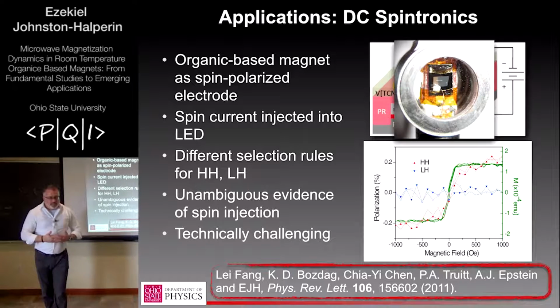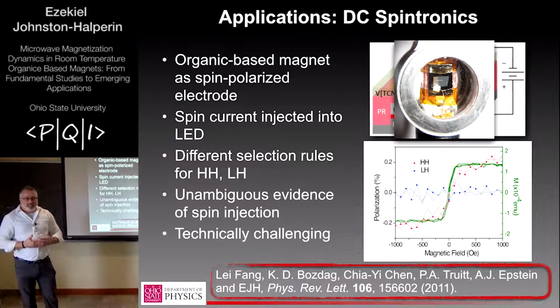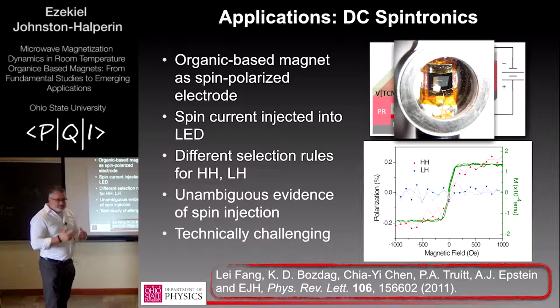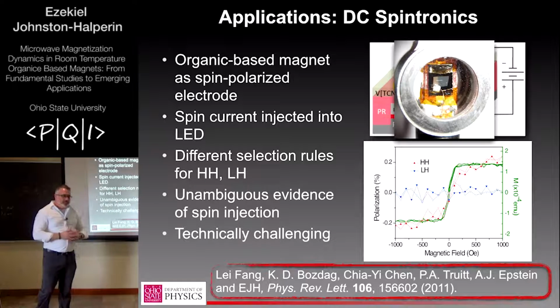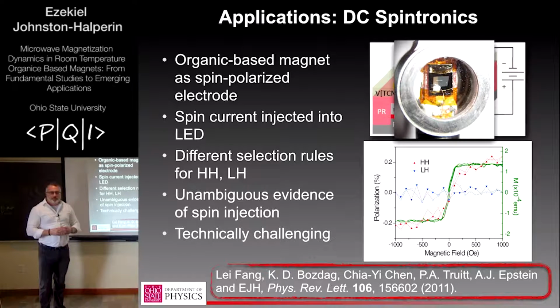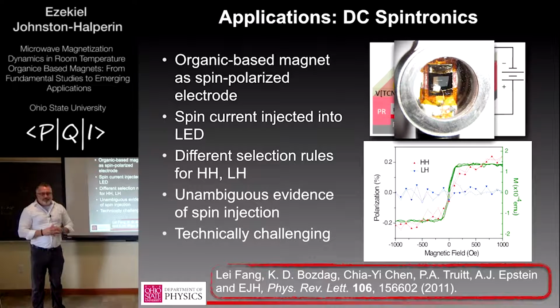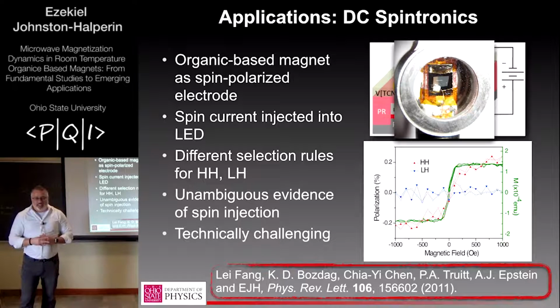Is that hermetically sealed with some O-ring? Yeah, it's got an indium ring. An indium O-ring, because we wanted to make it cold. What's it sensitive to? Oxygen? Both. And what's going to happen to the molecule? I'm not a chemist, so I can't tell.